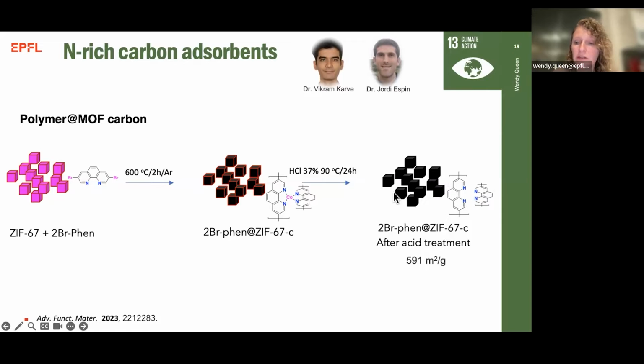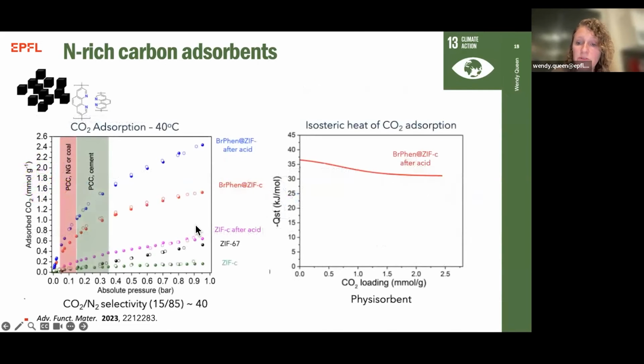But what we're left with on the back end is a highly porous carbon. It has a surface area of almost 600 meters squared per gram. And it has a very high density of micropores, so well below 2 nanometers is the pore size, but also a very high nitrogen content, which comes from both the MOF as well as the polymer that we've put inside. And so what we find is that this significantly enhances the CO2 adsorption properties.